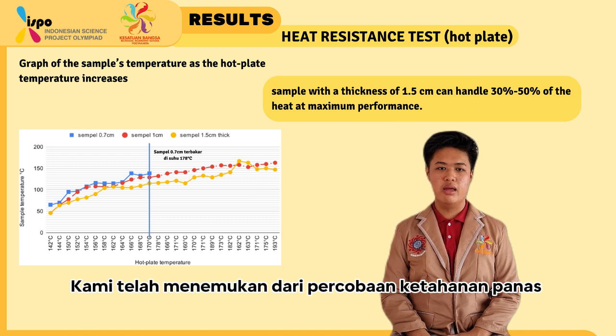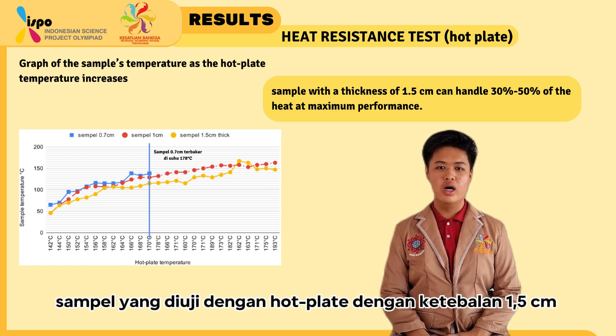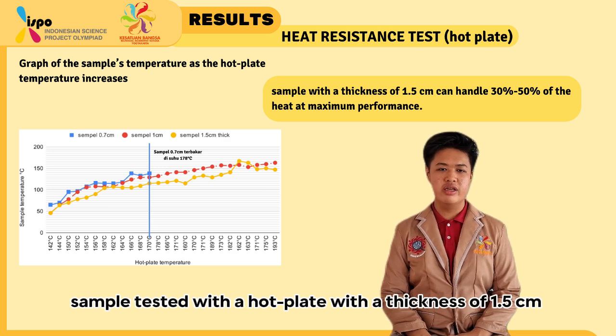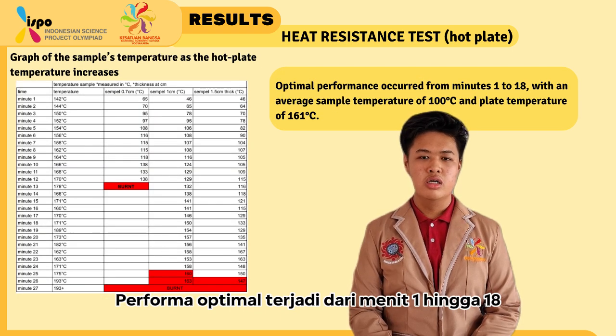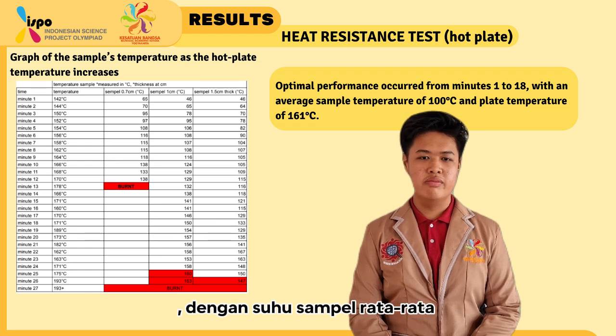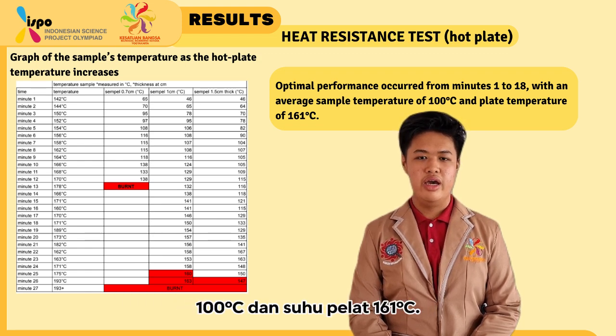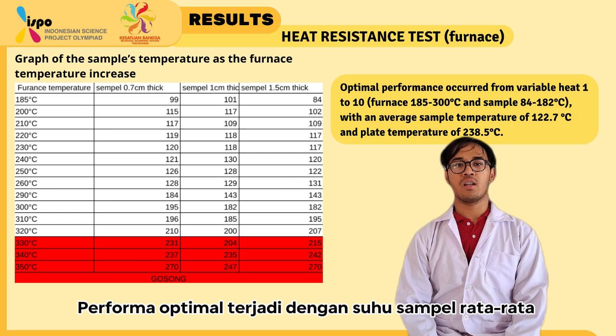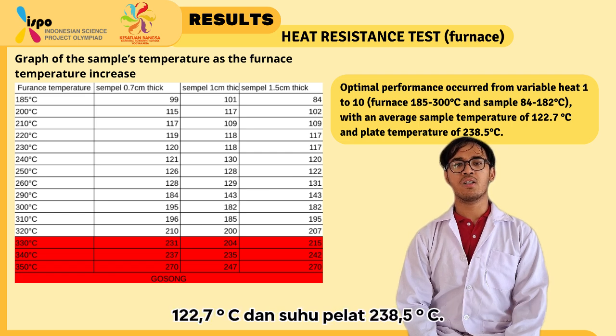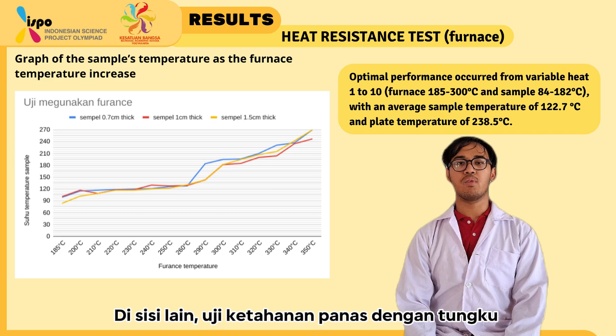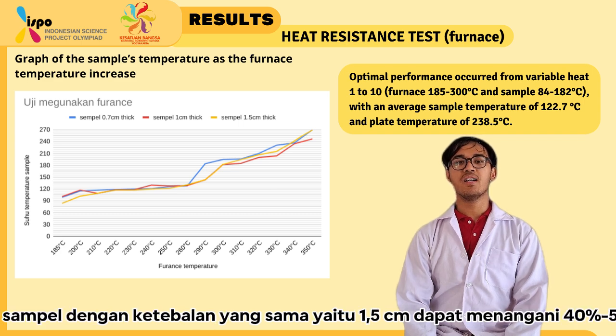and anti-radiation properties. We have found from the heat resistance experiment, the sample, tested with a hot plate with a thickness of 1.5 centimeters, can handle 30 to 50% of the heat at maximum performance. Optimal performance occurred from minutes 1 to 18 with an average sample temperature of 100 Celsius and plate temperature of 161 Celsius. Optimal performance occurred with an average sample temperature of 122.7 degrees Celsius and plate temperature of 238.5 degrees Celsius. On the other hand, the heat resistance test with a furnace and a sample with the same thickness of 1.5 centimeters can handle 40 to 50% of the heat at maximum performance.